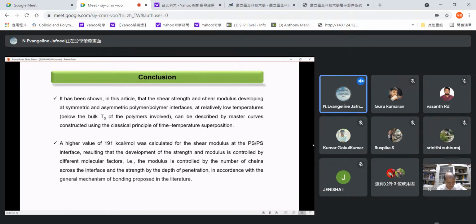Now, the conclusion. It has been shown that the shear strength and the shear modulus developing at symmetric and asymmetric interfaces at low temperature, below the Tg, can be described by the master curves. And the higher value of 191 kilocalories per mole was calculated for the shear modulus at the PS-PS interface, indicating that the development of strength and modulus is controlled by different molecular factors. That is, the modulus is controlled by the number of chains across the interface and the strength by the depth of penetration, in accordance with the general mechanism of bonding proposed in the literature.